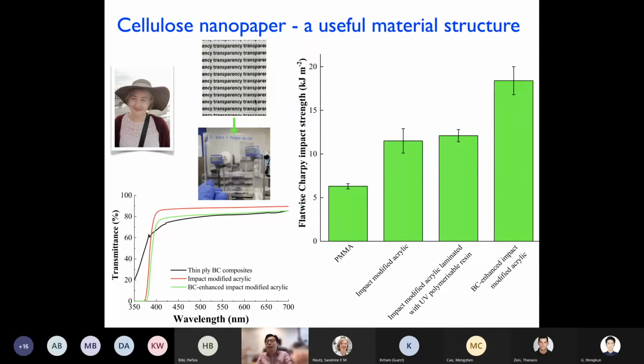We then laminate this in between impact modified acrylic. So this thing here has two transparent impact modified acrylic sandwiching that transparent film in between. So this whole structure here is 3 millimeters thick, and it's still transparent at the end of the day, as you can see either from this picture or from the transmittance versus wavelength graph, where within the visible light, you still have a transmittance of roughly 80%.